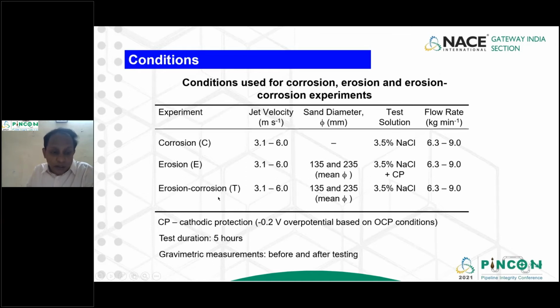Then I come to the third one, erosion corrosion. That is the combination of corrosion plus erosion. With these two combined, I will run the experiment. Now I remove the cathodic protection from here. I simply use the same velocity range, 3.1 to 6 meters per second, and a sand size of 135 to 235 micron at a flow rate of 6.3 to 9 kilograms per minute. I carried out this experiment.